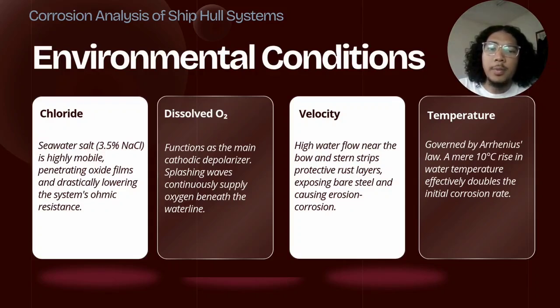They are driven by four primary environmental factors. Chloride, from the 3.5% salt concentration in seawater, easily penetrates protective films and lowers electrical resistance. Dissolved oxygen acts as the main electron acceptor, keeping the corrosion engine running. Velocity and high water flow, especially near the bow and stern, can physically strip away protective rust and coating. And lastly, temperature. Based on the Arrhenius law, just a 10 degrees Celsius rise in water temperature can effectively double the initial rate of corrosion.